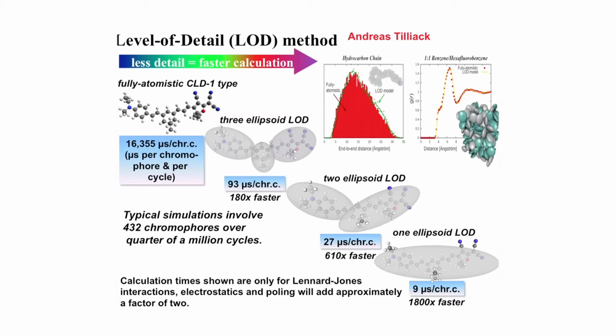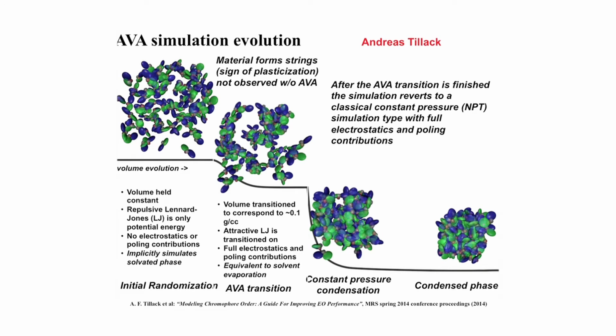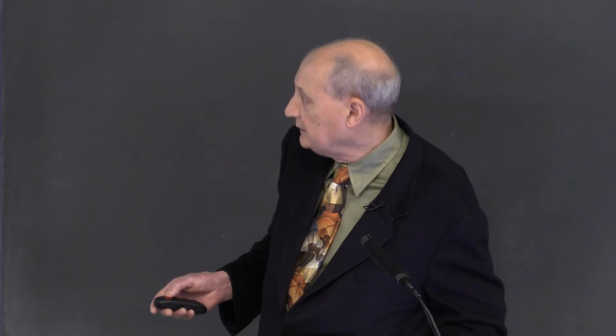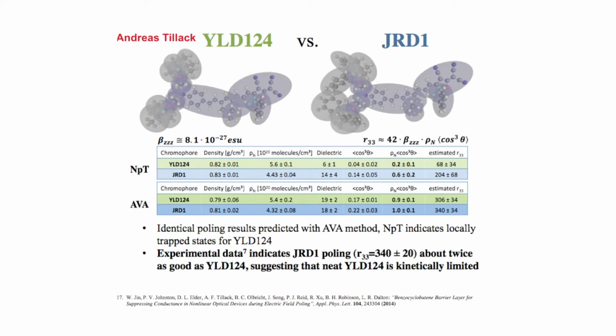The next thing that Andreas did that was really nice is he solved the problem of calculations hanging up in pseudo-minima. Remember, we're simulating the behavior in condensed phases. And so with these chromophores, a trajectory run may hang up in a non-equilibrium configuration that is characterized by a low acentric order. So what he does is model the process of going from solution or from the gas phase to a solid material, as for example would occur in crystallization, using this adiabatic volume adjustment method in simulation. And this has led to significantly improved simulation. For example, here using the adiabatic volume adjustment method, he simulates the experimentally observed poling value, while more traditional approaches underestimate the electro-optic activity obtained by poling.